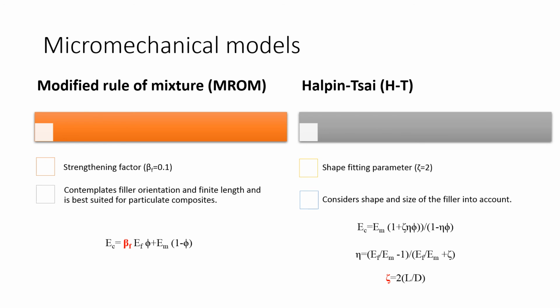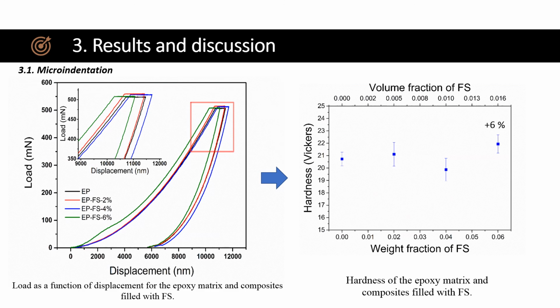The second model used was the Halpin-Tsai model. This model considers a shape fitting parameter, which takes the shape and size of the filler into account. Through the results obtained through microindentation, you can also determine the hardness of the as-prepared composites, as is shown in the figure to your right. You can appreciate that the filler with the highest amount of reinforcement, 6% in mass, has a 6% increase of its hardness.